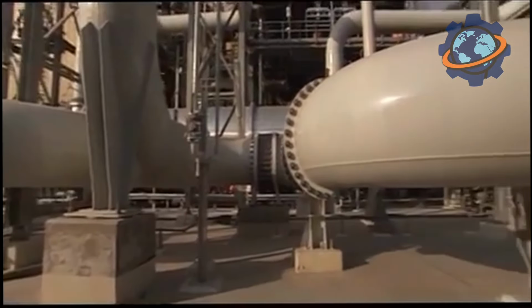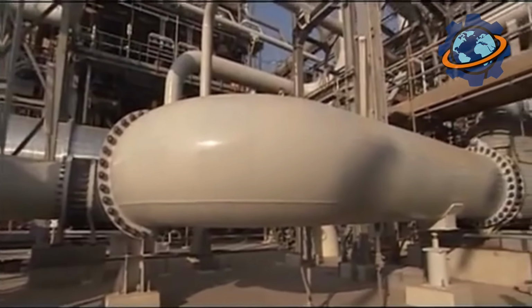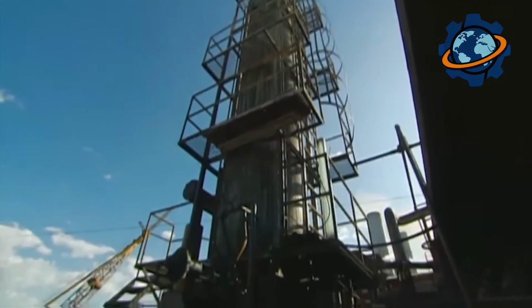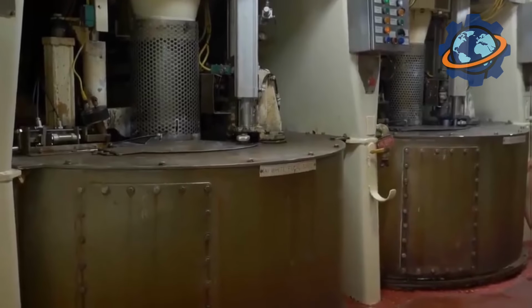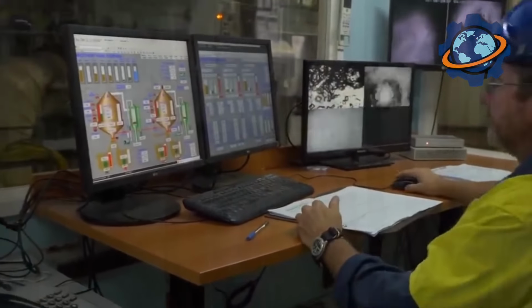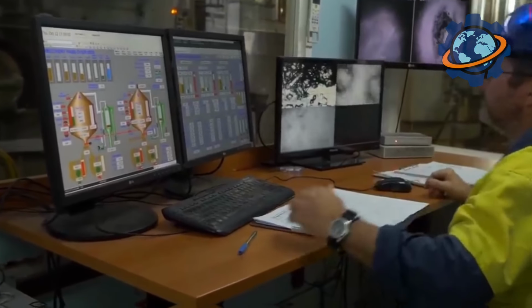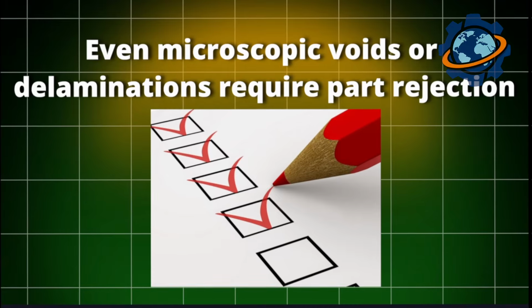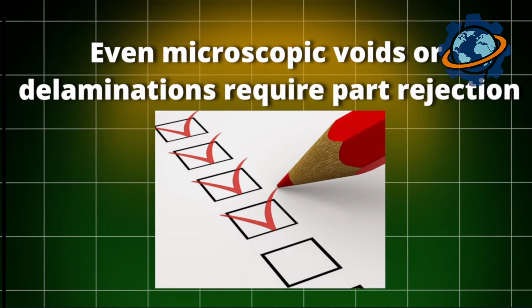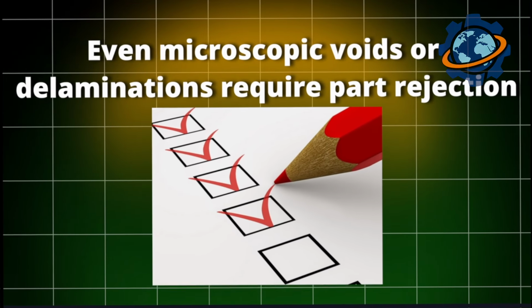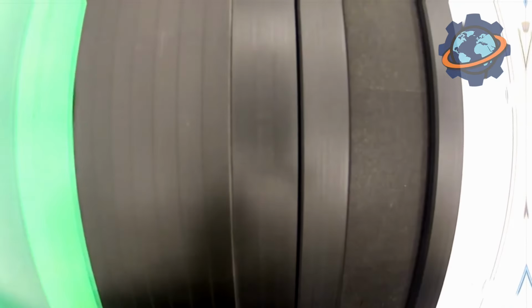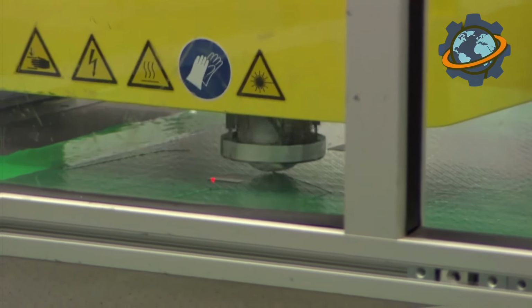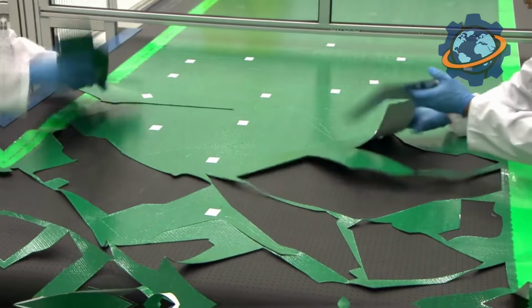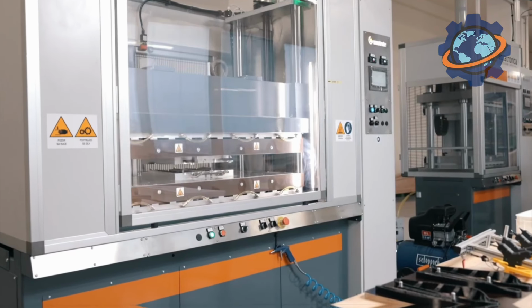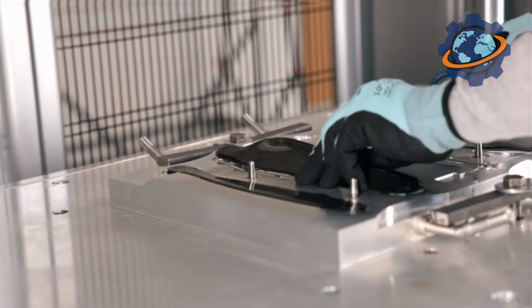After curing, parts exit as rigid structures, material properties now locked permanently. Non-destructive testing using ultrasound and X-rays searches for defects. Even microscopic voids or delaminations require part rejection because carbon composites tolerate 0 defects. Unlike metals tolerating small cracks through ductility, carbon composites fail catastrophically once cracks initiate. That brittleness demands perfection during manufacturing.